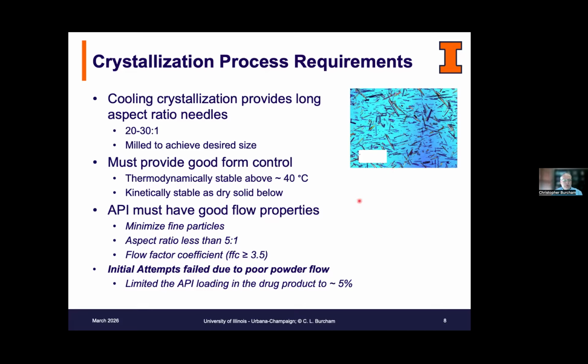It was greater than a 5-to-1 aspect ratio, which from the literature would say you would have better flowing material. And something called a flow factor coefficient, a measure of the ability for the powder to flow, where large numbers are necessary, was low. We were finding flow factor coefficients of around 2, where it's desirable to be above 3.5. And all this resulted in a limit of our drug loading to less than 5%, which would have meant a tablet burden for a patient of about 6 to 8 tablets.